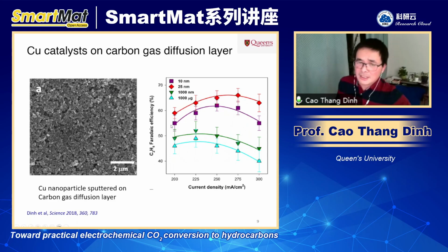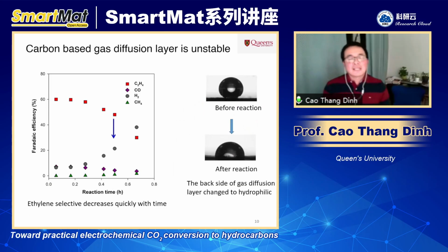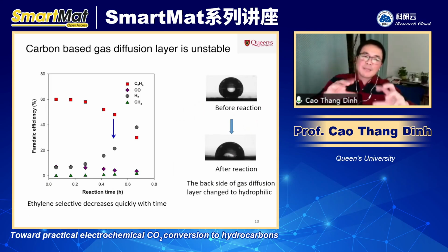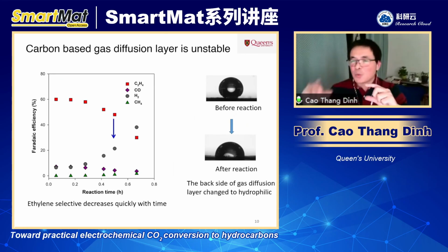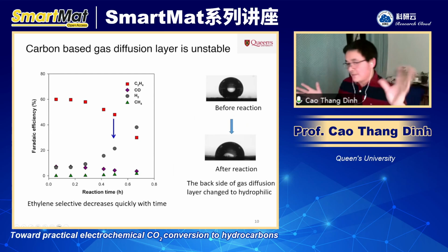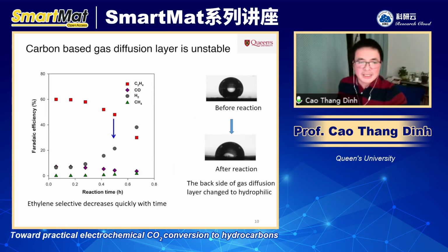So CO2 conversion to ethylene with a Faradaic efficiency of 50 to 65%, which is pretty high for a current density of around 200, at that time. Now people report 70, 80%, but by that time it was pretty high. Now the problem with this is when we run the stability test, where we keep the reaction at a fixed current and monitor the products over time, as you can see here, the ethylene selectivity dropped pretty quickly after half an hour or so. At the same time, the hydrogen keeps increasing. Methane and CO stay pretty much the same, right? So this suggests that something happened.